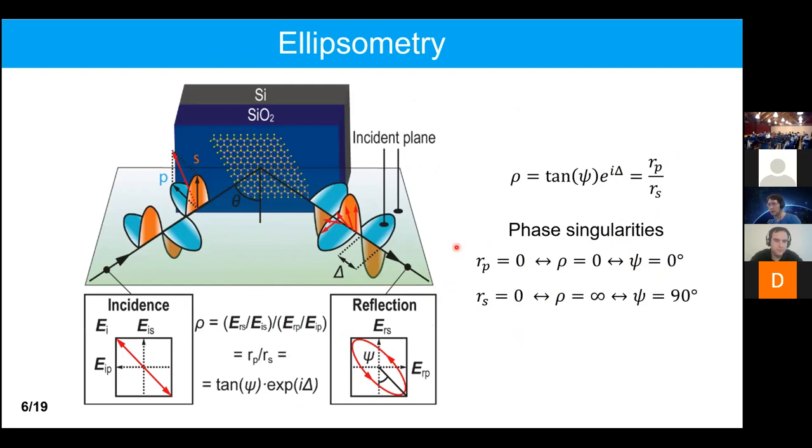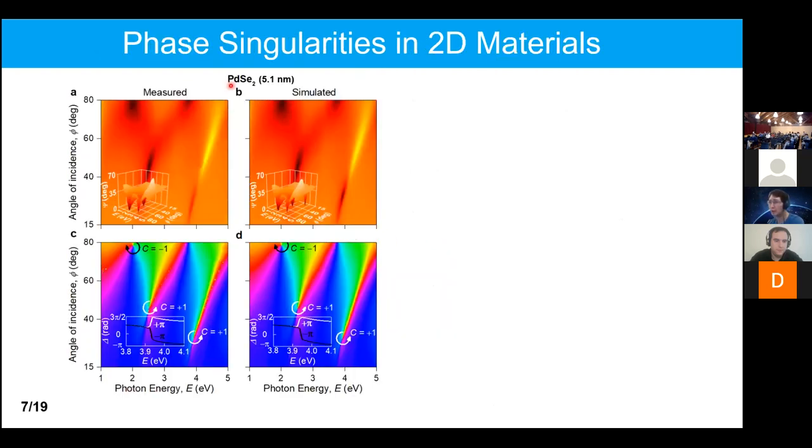So we did the experiment. And you see, for example, for a thin film of palladium diselenide, these topological points of zero reflection. And you see that indeed, at these points, we have a topologically mapped phase variation. More interestingly, at some points, for example here, we didn't achieve exact zeros in the experiment due to experimental non-idealities, but nevertheless we have this topological phase because of the topological protection of our structure, because of the intersections of the material's curves and the zero reflection surface, which I showed.